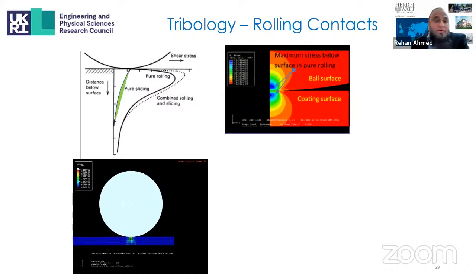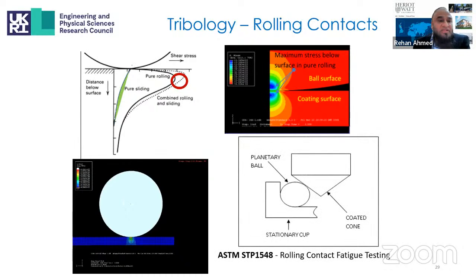So that's a little bit about sliding contacts. We can move on to a slightly different type of contacts, which are the rolling contacts. And the main difference between the rolling contact and the sliding contact is that in pure sliding, the coefficient of friction is much higher and the maximum stress appears on the surface. Whereas in pure rolling contact, the maximum shear stress, or the stress driving the cracks for fatigue and delamination, is subsurface, as can be seen over here,